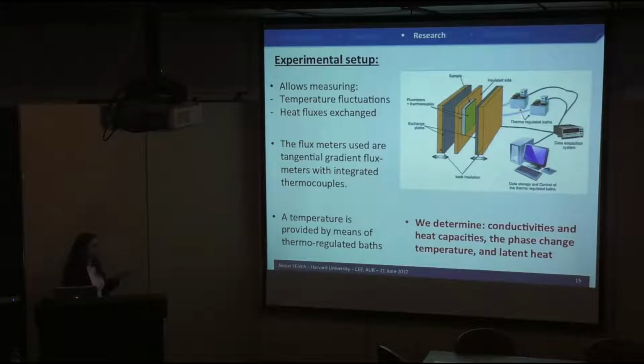This is connected to the data acquisition system where we can extract the heat fluxes and the temperatures of each phase. From analyzing the data of heat fluxes and temperature curves, we can determine the thermal conductivities of both solid and liquid phases, the heat capacities, and also the phase change temperature and the latent heat. I'm not going into details of this method because it is a direct integration of the curves to obtain these properties.